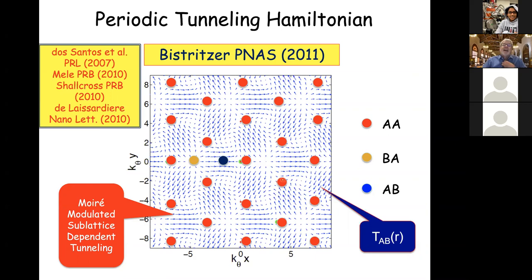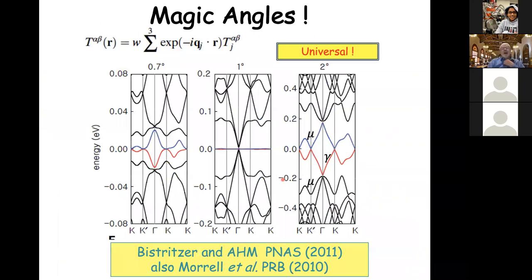And so if you use the twist angle in units as you like, there's really no preferred scale. For a particular value of this dimensionless twist angle, which you put in the real scale of the interlayer tunneling, which as I mentioned a moment ago is around 1/3 of an eV, it turns out that a particular value of the dimensionless twist angle, which in dimensional form is around 1 degree,